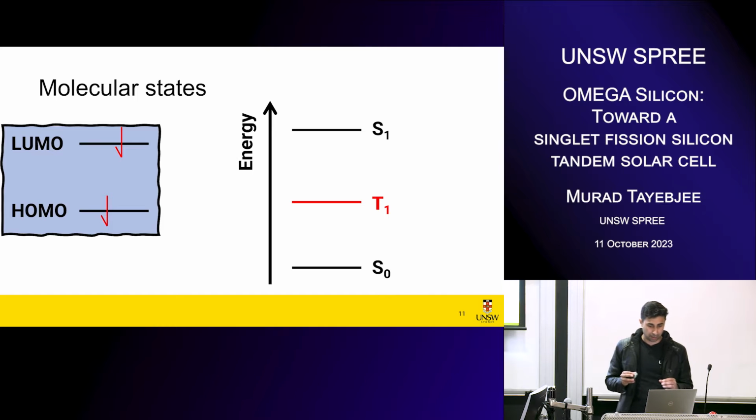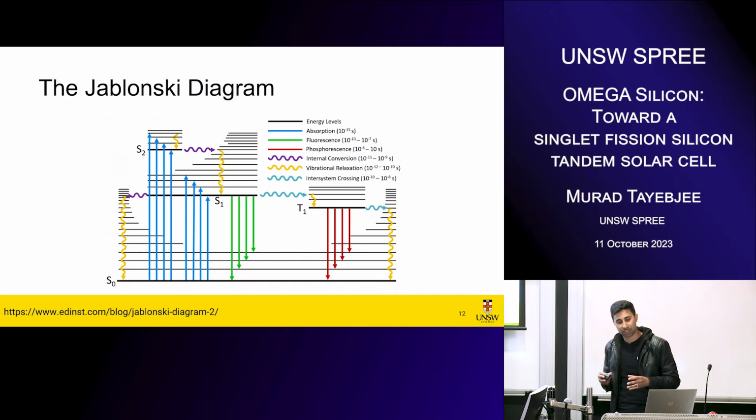And the following diagram is going to tell you how you get from one state to the next. It's very, very intense, so I'll break it down slowly. Remember how I said intersystem crossing is spin forbidden? Well, it turns out molecules are quite naughty, and they do forbidden things hundreds of millions of times per second. Intersystem crossing actually does occur quite quickly, but it just gets outcompeted by all the other processes. So intersystem crossing from your singlet to your triplets is on the order of microseconds, whereas fluorescence from your singlet to the ground state is on the order of nanoseconds.